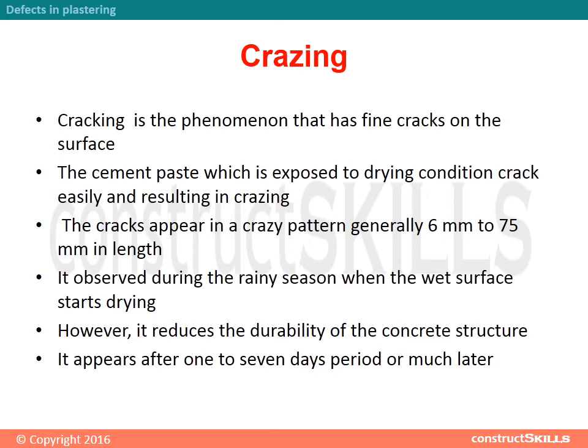Crazing: Cracking is the phenomenon of fine cracks on the surface. The cement paste, when exposed to drying conditions, cracks easily, resulting in crazing. The cracks appear in a crazy pattern, generally 6 mm to 75 mm in length, and are observed during the rainy season when the wet surface starts drying.